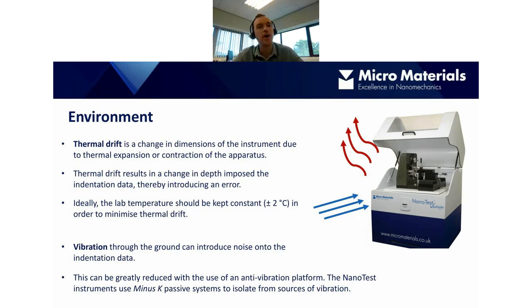So the other environmental factor is vibration. The key thing with vibration and also thermal drift is that with nanoindentation, we're measuring on a nanometer scale. We can be doing indentations that have a maximum depth of less than 100 nanometers, or even less than, say, 20 or 30 nanometers. So any vibration through the ground or even through the air can introduce noise, very spiky looking indentation curves, which can affect the hardness and modulus values that you measure.